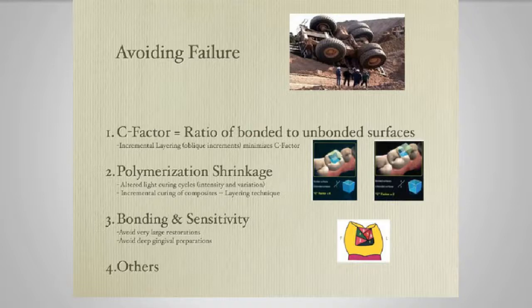Now, there are some ways we can combat this C factor, and the best way that's been shown is through incremental layering, the oblique increments. I'm showing a picture there on the bottom right. Now, that one's a little bit overkill, but you kind of get the idea: by placing layering increments in an oblique fashion, this tends to minimize the C factor stress. And this can also be done in a class 1. A lot of my class 1s, even when they're shallow, I'll still tend to place them in 2 increments to allow for this incremental layering to minimize the C factor.